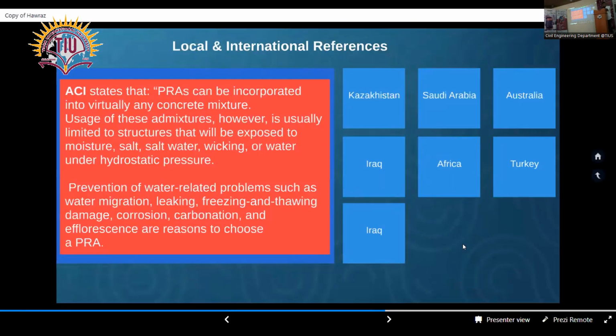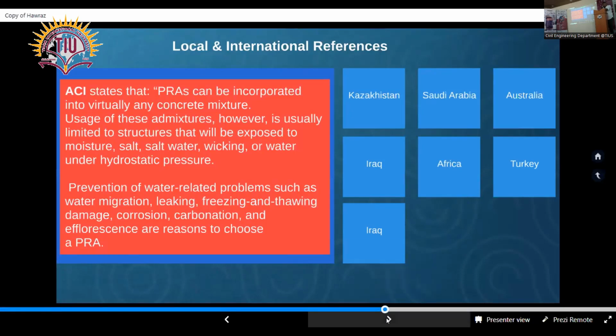The ACI code clearly states that the permeability reducing admixture can be incorporated into any concrete. However, usually it is incorporated into concrete which is exposed to a critical environment. Critical environments we have in the basements of buildings, in water tanks, and even concrete slabs exposed to weather are considered a critical environment. Penetron admixtures are used to eliminate the problems of water migration, leakage, freeze and thaw, corrosion, and carbonation. Actually, we have many references around the world and in Iraq, but I could only prepare about 5-6 samples.